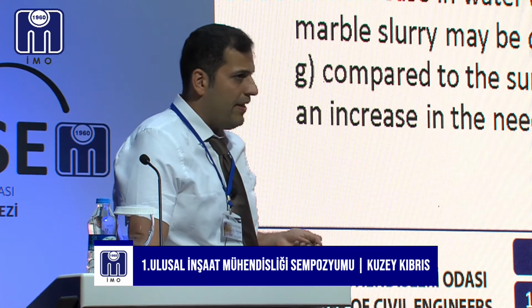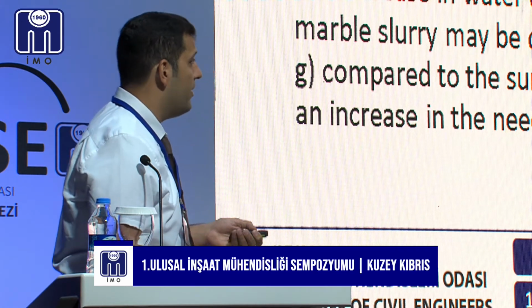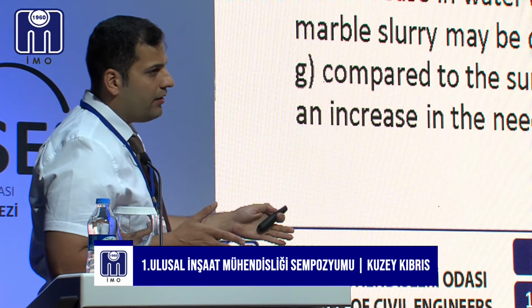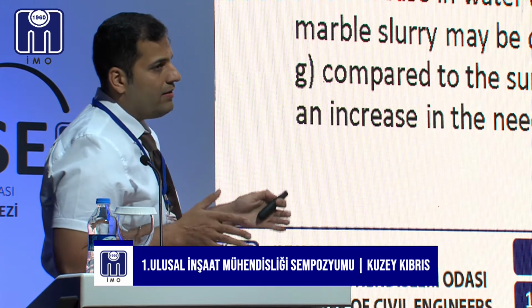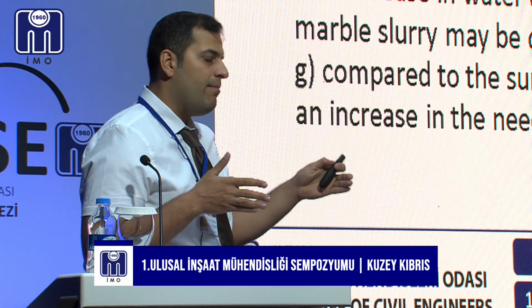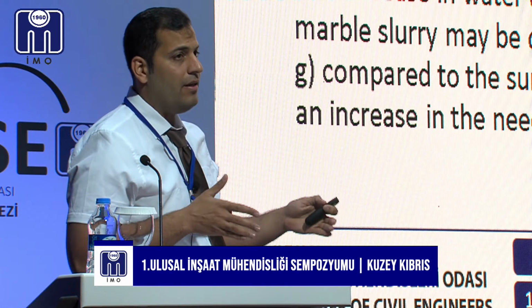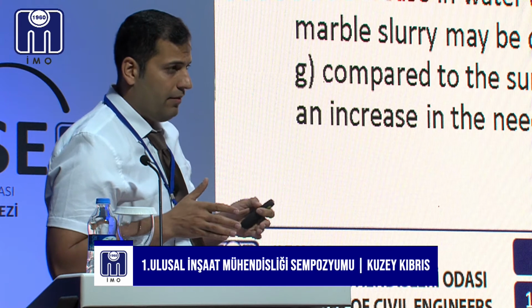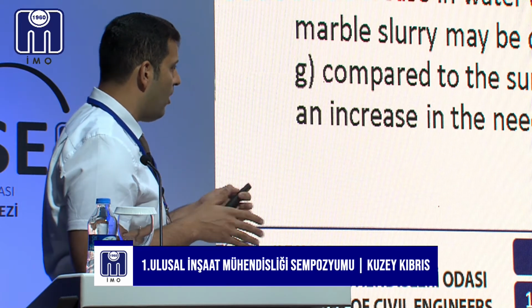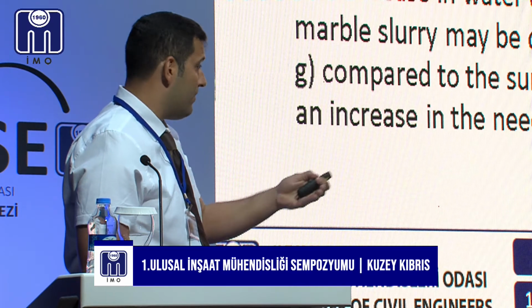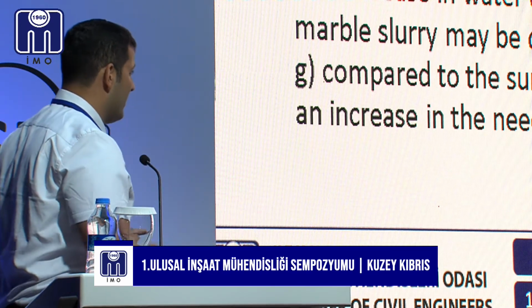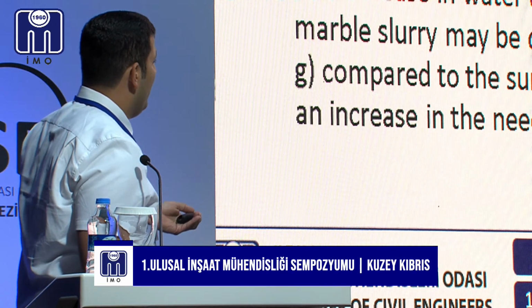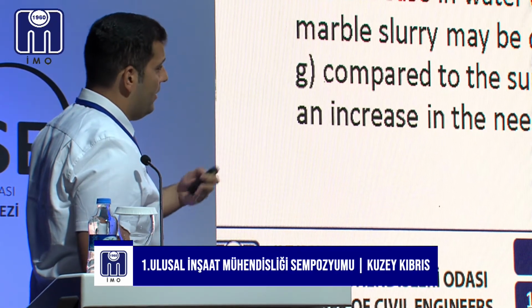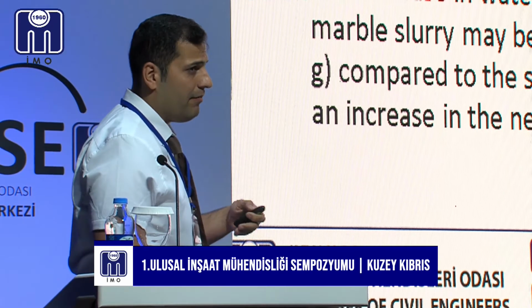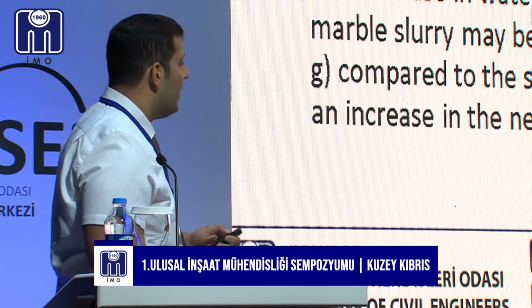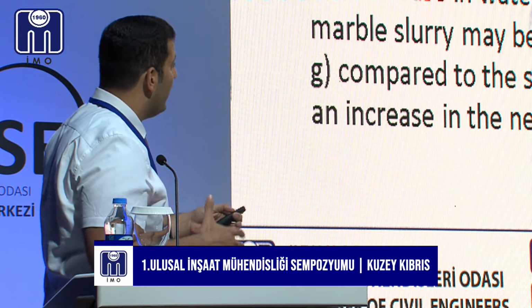The first question might be based on the workability of these two materials. Out of the 100 articles that we went over, 99% mentioned that adding this material will decrease the workability of the concrete. However, a few articles showed that it was increasing. It might be based on different reasons. By the way, when marble dust and granite dust are smaller than 75 micrometers, this decrease is shown more clearly.